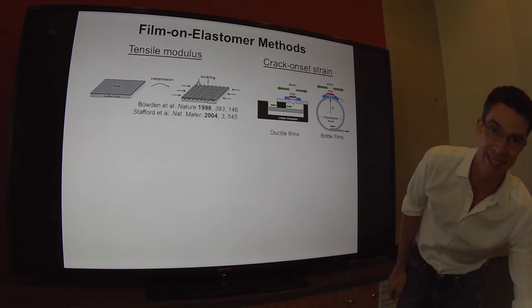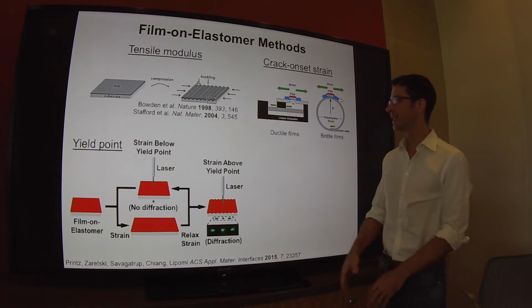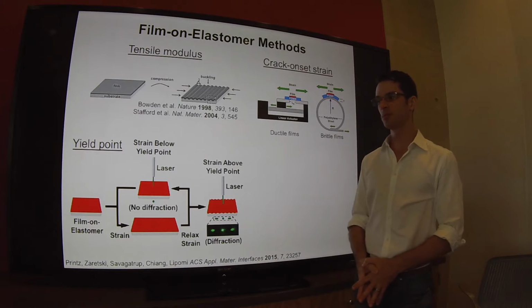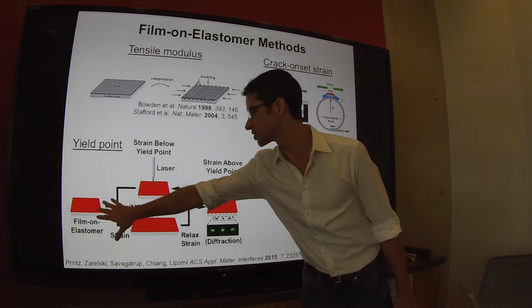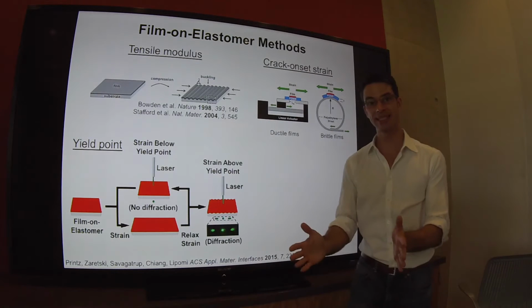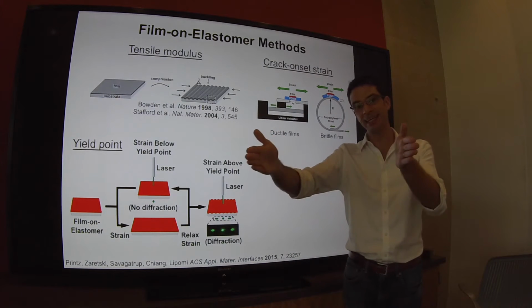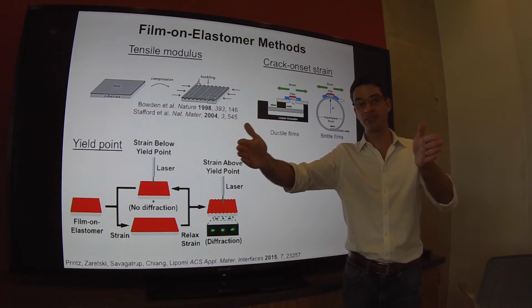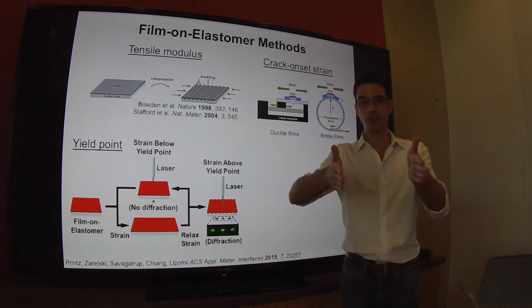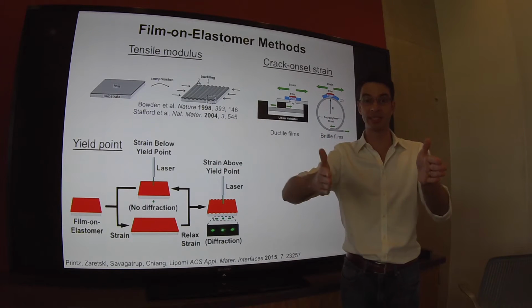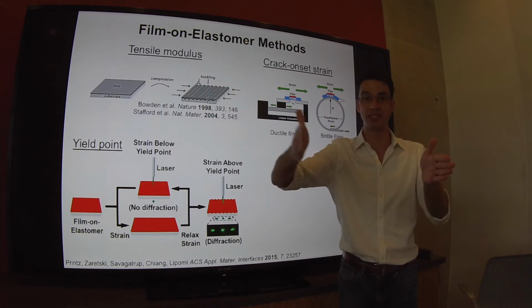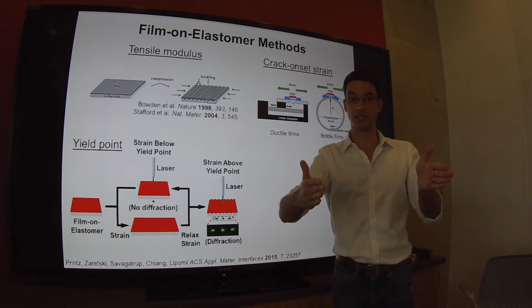And that gives you an idea of the fracture energy. And you can even approximate the yield point, first by putting the structure of the film on an elastic surface and then increasing the amount of strain incrementally, so from 0 to 1% to 2%, back to 0, back to 3%, back to 0, back to 4%, back to 0, and so on.